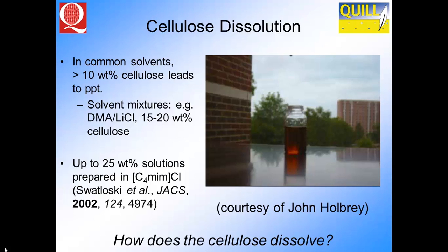Can you use ionic liquids? This is a piece of filter paper being put into hot BMIM chloride at around 100 Celsius, and it dissolves pretty well — the result is a transparent material. To get the cellulose out, you simply add water and the cellulose precipitates. If you control how it precipitates, you can make fibres, sheets, and so on. It's a much simpler way of doing this processing than using sodium hydroxide and sulfuric acid treatments. What we were interested in was how does this cellulose dissolve? Although we couldn't look at cellulose itself, we know cellulose dissolves better in acetate-based ionic liquids than in chloride-based ones.